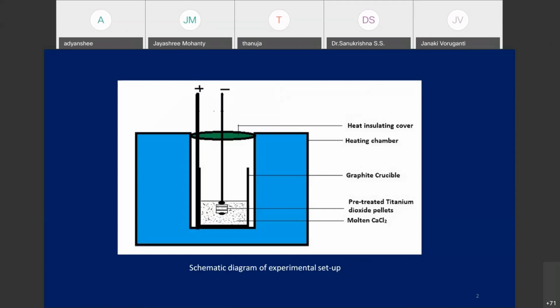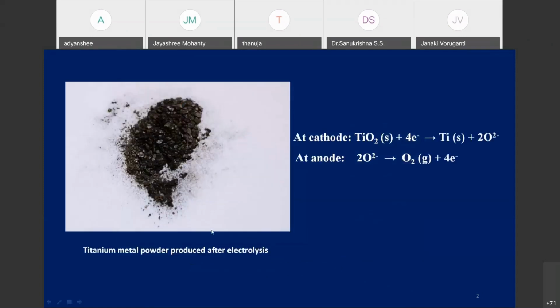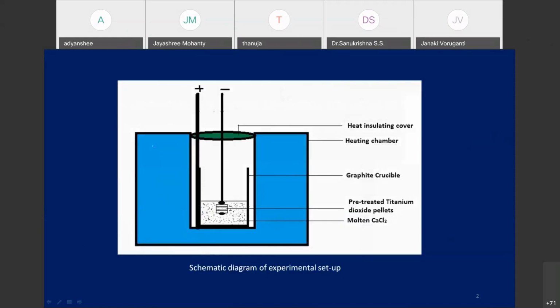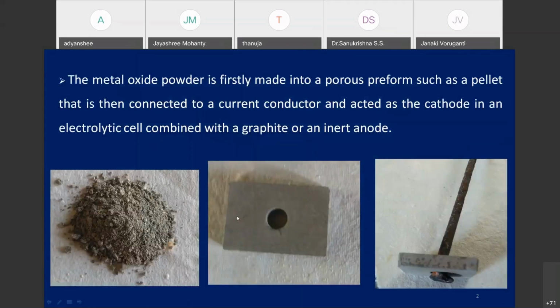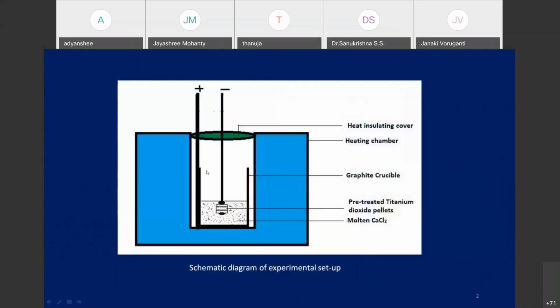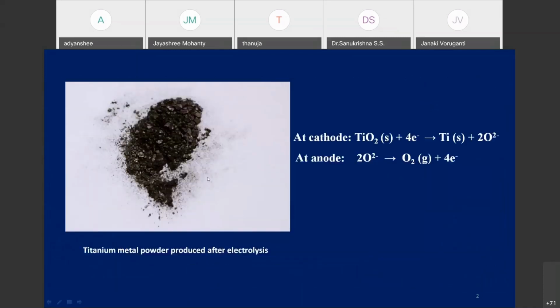I've shown you one typical example of preparation of titanium metal from titanium dioxide directly. You can see here, this is actually a pre-treated titanium dioxide material, and after reduction, I am getting titanium powder like this. So directly in the solid state, you can produce the metals, without the molten state condition like in the Hall-Heroult process.